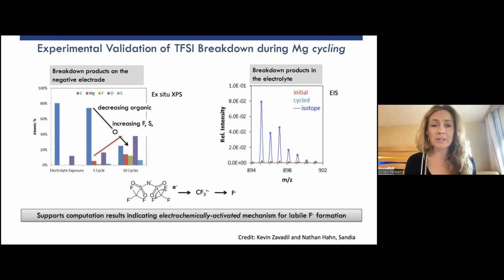We always need to validate with experiments. We had really good collaborators in Kevin Zavadil and Nathan Hahn at Sandia, and they were able to do ex situ XPS of, in this case, a platinum surface, where they just exposed the electrolyte, some magnesium TFSI in diglyme, to the interface. And they looked at the interfacial species, and they were just made of carbon and oxygen to begin with, which might be coming from diglyme or the atmosphere. But as they started plating magnesium and cycling the electrolyte, they saw a buildup of fluorine and sulfur species, which really only can come from TFSI, which indicates that there's an electrochemically activated process